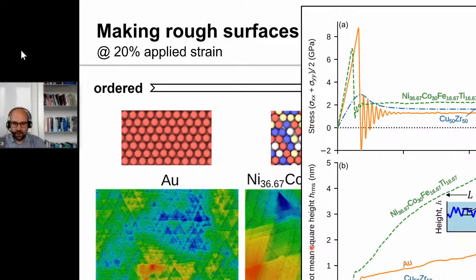This is the root mean square surface height, the amplitude of the height fluctuations. If this is a line scan of our height, it would tell us by how much the amplitude varies. I'll show that to you in a second as a function of scale. This is the height measured over the full size of the samples that you see here, which were initially 100 nanometers by 100 nanometers. You see that the roughness increases as we strain it, but yield is the point where it emerges first. So before the material has yielded, in the elastic regime, there's no surface roughness.